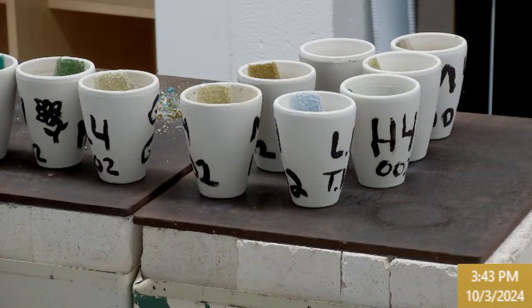And so over time, small flux like lithium, it's really potent. At least I'm assuming that's part of what I'm seeing. But we discuss those, and I've got pictures of them in the lab, because the more potent that positive charge is, the more effective it is at disrupting polar covalent silicon oxygen bonds and infiltrating that through a process called fluxing of the glass. And even though they're all just alkali cations, lithium at the same concentration is more potent than sodium, which is more potent than potassium at the same pouring temperature.